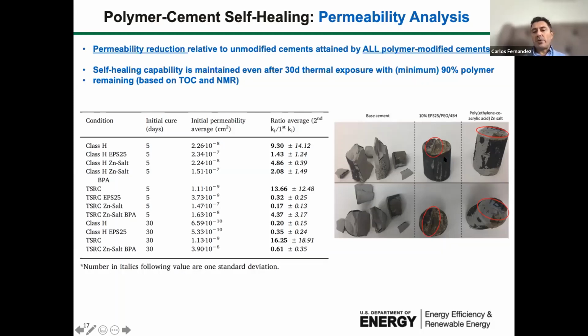But when you do that with the polymer modified cements, you just displace, generate the fracture, and then you can put the pieces together. And after 24 hours at 200 Celsius in some cases, or 300 Celsius for the second formulation, you end up with the healed fracture. So here, what we see is the class H cement and the TSRC. These are the control cements without any polymer. And we can see the ratio of the permeability after healing and before, when the fracture is generated, is higher in all of the control cements.